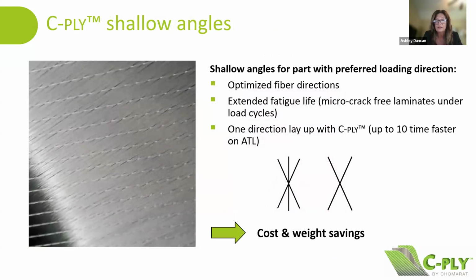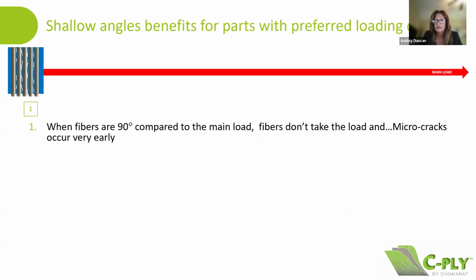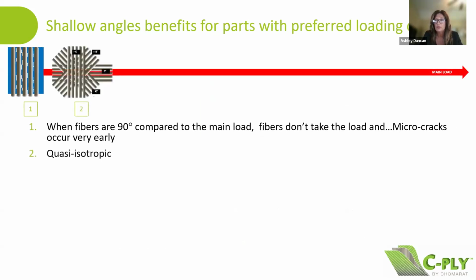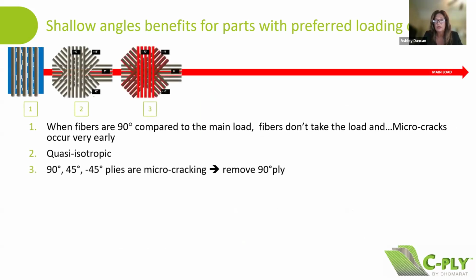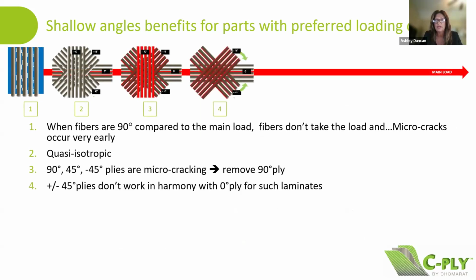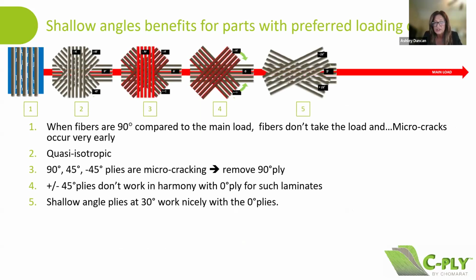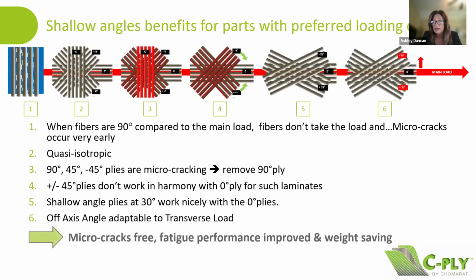So moving along, the second C-ply specialty feature that I want to discuss in more detail is incorporating shallow angles. What do I mean by incorporating shallow angles? Well, a shallow angle provides the ability to optimize fiber in the preferred loading direction. So this is another visual slide. It depicts the value of incorporating shallow angles in the preferred part loading direction to improve fatigue performance and also reduce part weight. In this illustration, the red arrow, let's just call it heading eastbound at the top, represents the main part loading direction. This could be a spar section or a wing section, just something longitudinal.